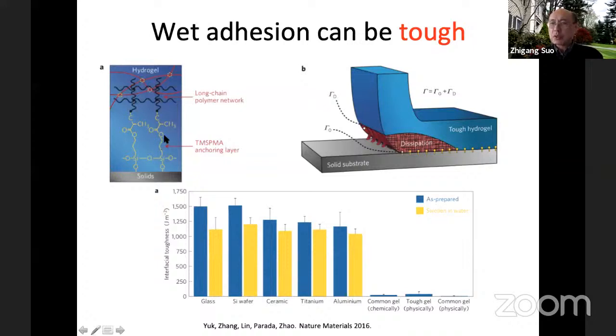That's fairly traditional in the literature—if you look at the literature, people just didn't say this clearly. But the other idea was very well known to mechanics people, though not really known to people doing hydrogel work. This is about dissipation. If you want high toughness, you need to build in some plasticity in your gel, so that before the strong bond breaks, you cause plasticity and dissipate a lot of energy.